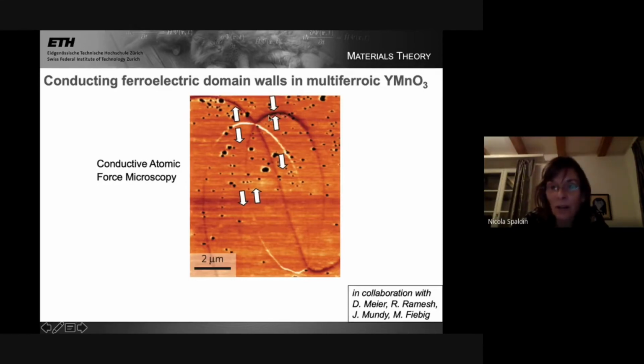This dark color means there's less conductivity, and that's because all the holes have gone away and come over here. So the fact that the positive holes deplete from this region screens the diverging electrostatic potential and gives an absence of carriers. And then in this region where the dipoles are parallel to each other, you don't need any extra carriers, and the conductivity is just the same as the background.